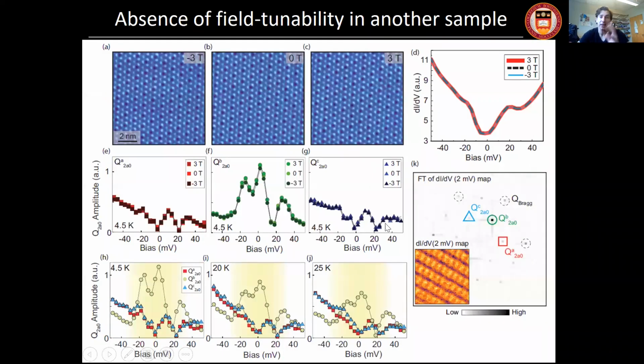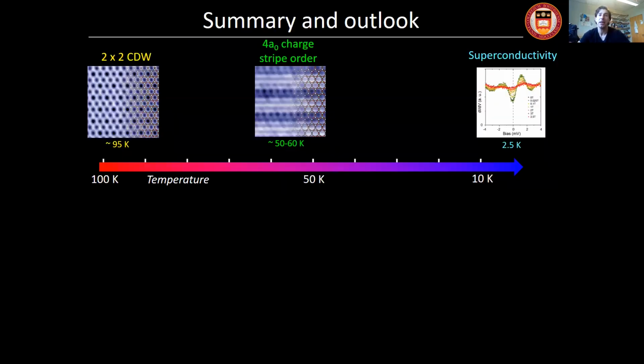This is another data set. We check to make sure there are no tip changes, based on the dI/dV spectra looking nearly identical at different fields. All these amplitudes are very close at different fields. So we are pretty confident that the majority of the areas of the sample do not exhibit any sort of magnetic field coupling as far as the CDW is concerned.